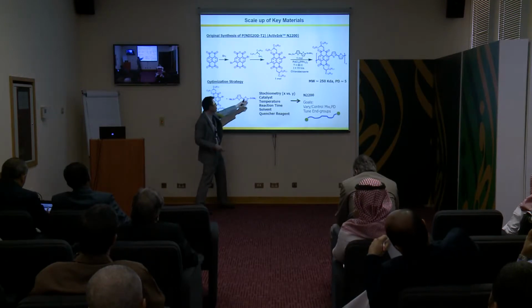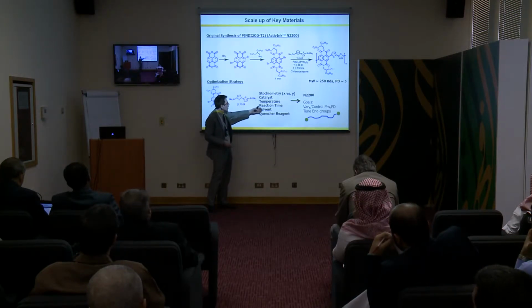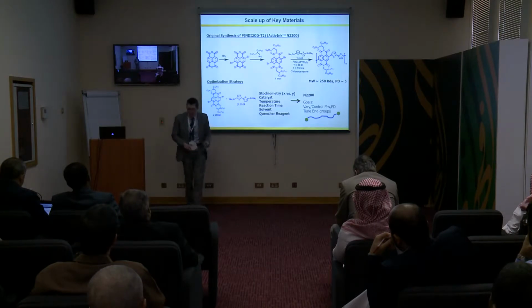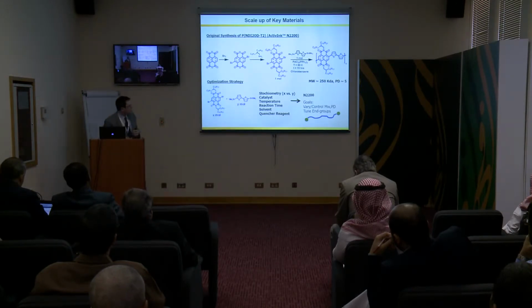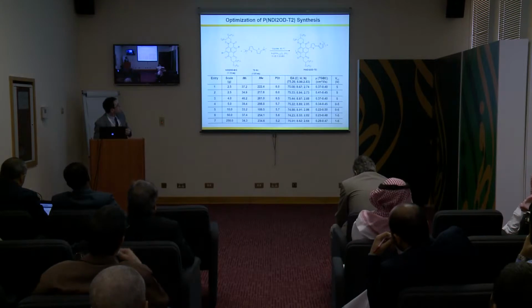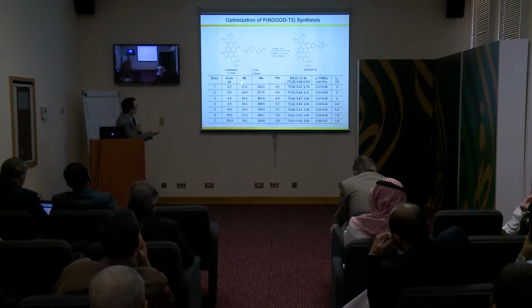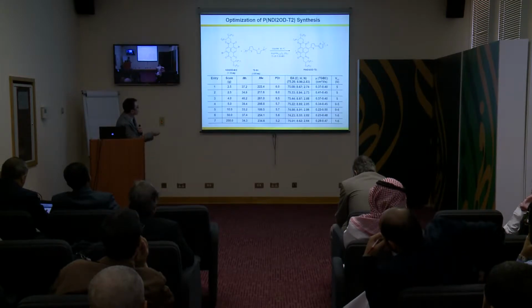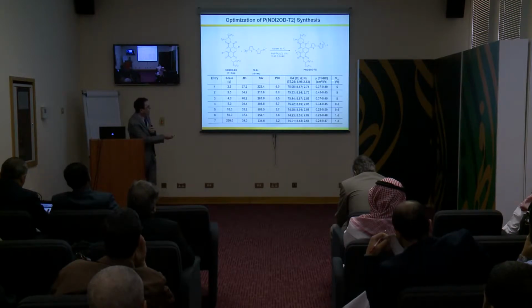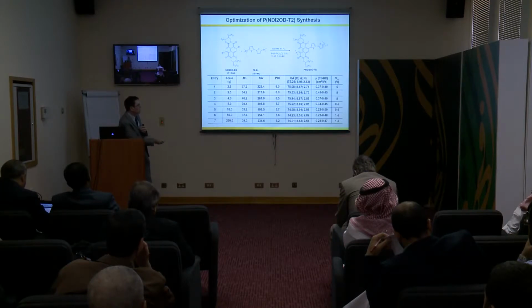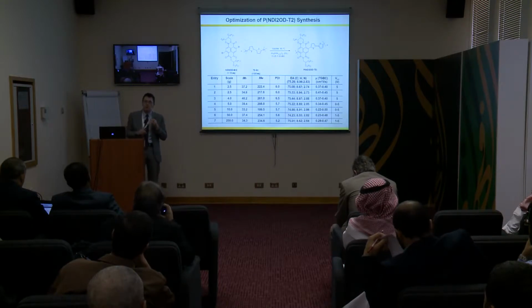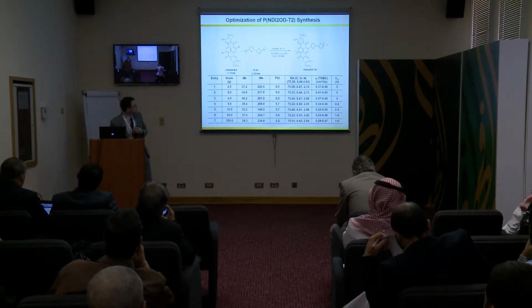We had to do a fair amount of work in optimizing the stoichiometry, the catalyst, the reaction times, the conditions. But we have been able to scale up this chemistry from a few grams to a quarter of a kilo, maintaining the very good control in terms of molecular weights and transistor performance, also in a very similar range. So it's a chemistry that can be scaled up for those of you who are interested in organic synthesis.